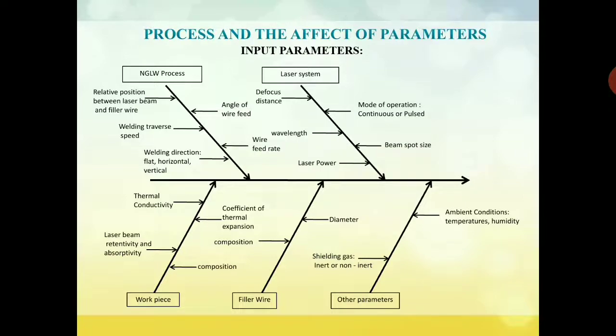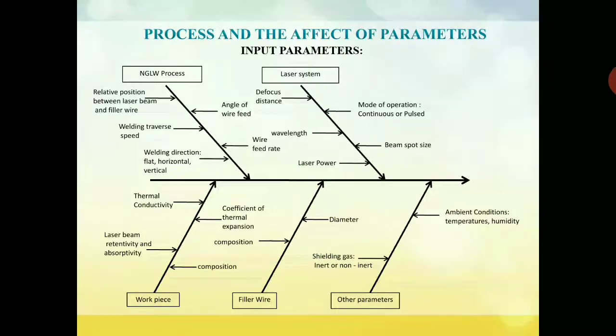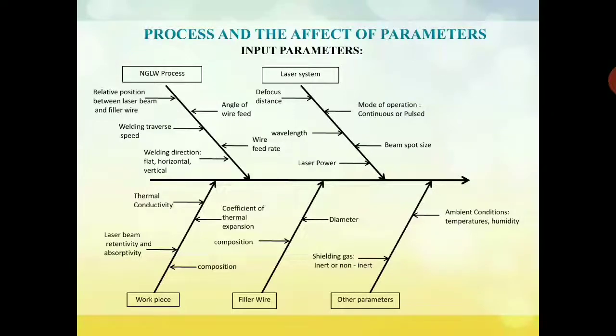Speaking of laser, a high power laser produces metal vapor, hence the power must be optimized. Also, using a defocused laser beam provides a larger defocusing distance, thereby leading to direct energy transfer, which in turn melts the sidewall. The main characteristic of the shielding gas is to effectively isolate the weld zone from the atmospheric contamination. Moreover, the consumption of shielding gas is reduced significantly when it is directed inside the groove. To obtain a smooth weld seam, it is also important that the droplet transfer is in the surface tension mode.